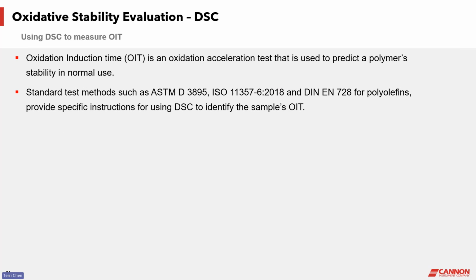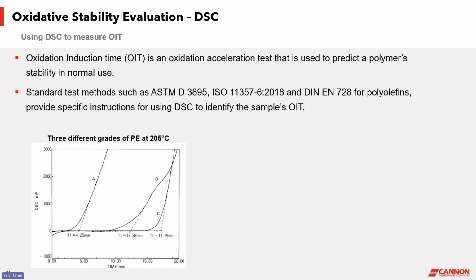DSC is commonly used to determine the oxidative stability of a polymer. There are some industry standards, such as ASTM, ISO, or DIN standards. They all provide specific instructions for using DSC to identify the OIT of polymers. OIT means oxidation induction time. This is a standard DSC test method to study the time for a polymer to start getting oxidized at a certain temperature. The figure on the left side shows the OIT test of 3 different grades of polyethylene resins.